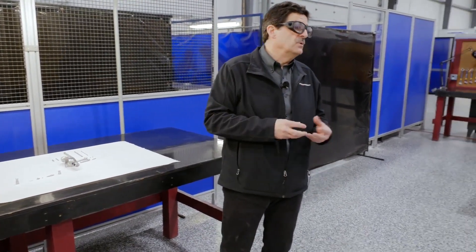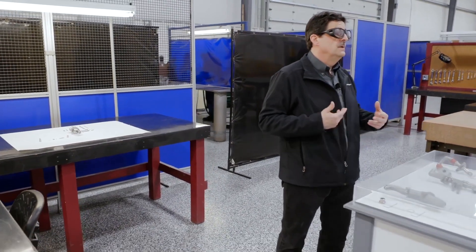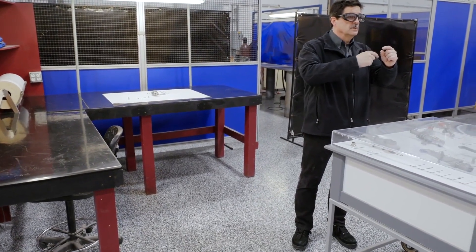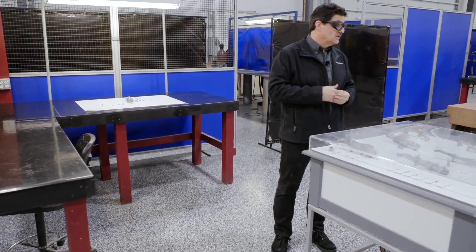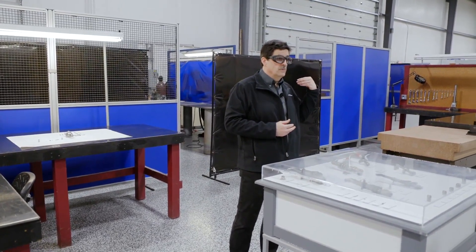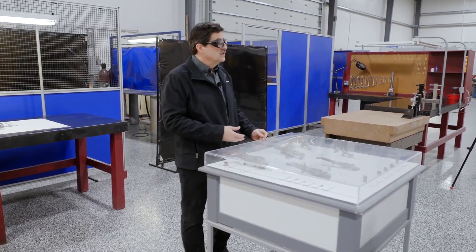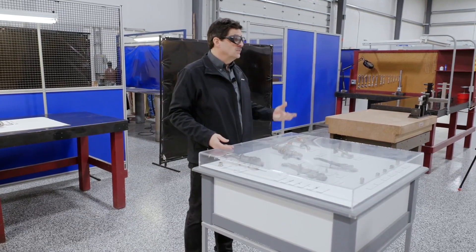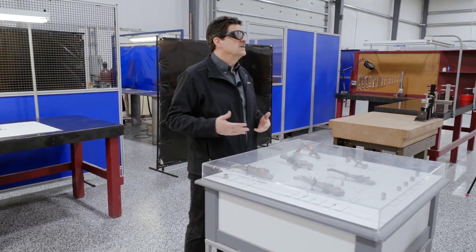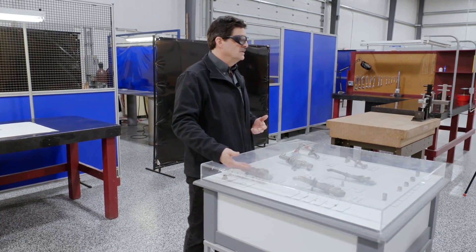There's a series of operations. We have some cylindrical welding equipment that allows us to do the circular welds around the nozzle — those welds are critical to getting the right seal. There are also brazing steps, so parts do go over to the main facility for vacuum furnace work and some inspection work. Because the work here has another level of cleanliness requirement, we have a special shop with our own clean line, which allows us to do specialized cleaning as well as rinsing and drying.